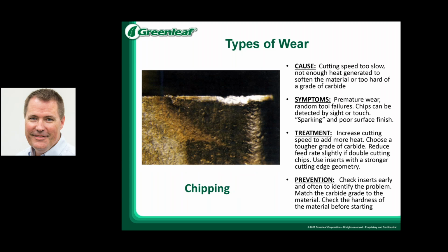Chipping. This is commonly seen where you'll see notches along the edge. This is where small pieces of carbide actually end up getting pulled out, removed from that cutting edge. It can be acceptable to a certain point as long as you know when to expect it. If chipping is observed, it can increase in severity the longer you're in cuts.